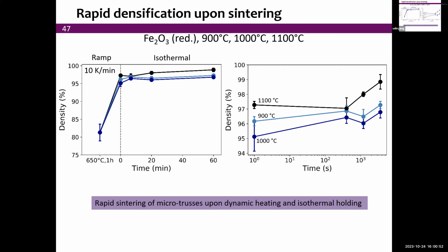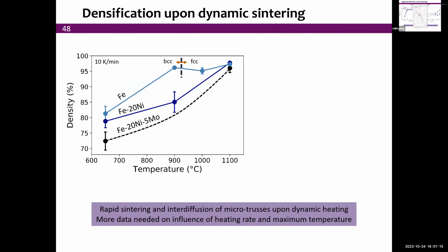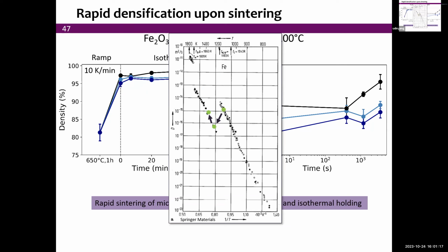We see that as we go from 900 to 1,000, actually the sintering is less good. Increased temperature, and yet sintering is not as good, which is unexpected. Normally, increasing temperature means faster diffusion and therefore faster sintering. Only when we go to about 1,100 degrees C do we get an improvement. And we're kind of scratching our heads, but the reason for this is the phase transformation.